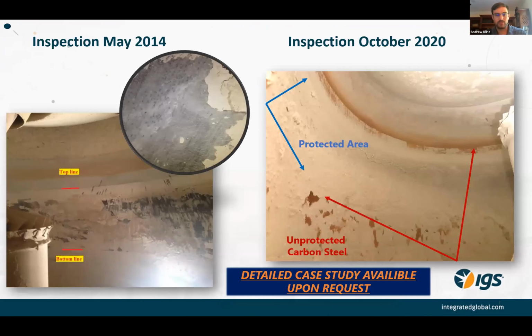Now, it was inspected in May 2014, which is a relatively short time period after the installation. But when it was inspected and the slagging was removed from the wall, it was clear that there was no discoloration or anything like that to indicate corrosion. And we were actually able at that time to use an Elcometer to do some spot checks of thickness, and there was no thickness loss off the nominal thickness.